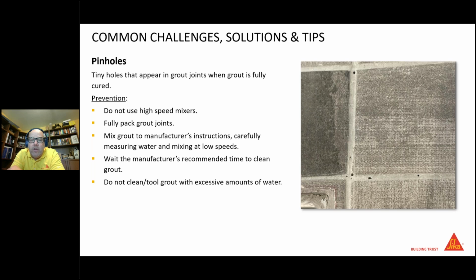Again, we want to make sure the grouts are fully packed grout joints. We want to mix to the grout manufacturer's instructions, carefully measuring water. I'm always going to say that. Always measure water with grouts, mixing at low speeds. Wait the manufacturer's recommended time to clean the grout. Don't get on it too soon. And then do not clean or tool grout with excessive amounts of water. We want to make sure, again, that the sponge is damp, not wet, and we're using as little water as possible to clean these joints.